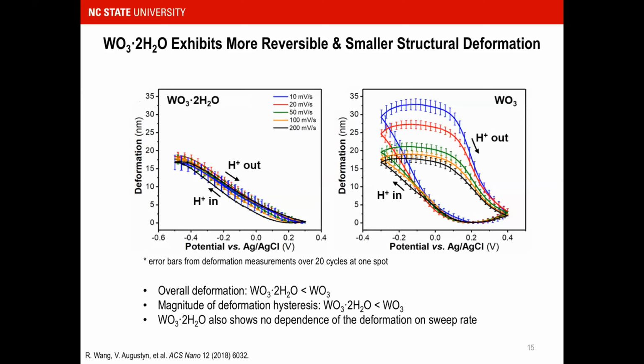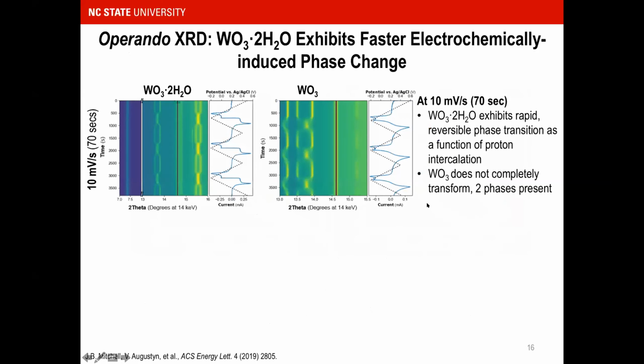There was also this very interesting lack of sweep rate dependence. So we don't see any differences on the deformation, no matter how quickly we scan between the potentials, whereas for the anhydrous material, we do. And when we coupled this result with operando X-ray diffraction, this was now done at the SSRL, the Stanford Synchrotron Radiation Light Source, we found that what we were observing in the AFM was really the fact that the hydrated material exhibits a much faster electrochemically induced phase change.